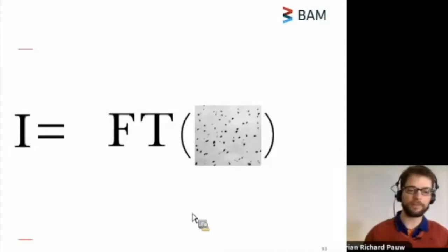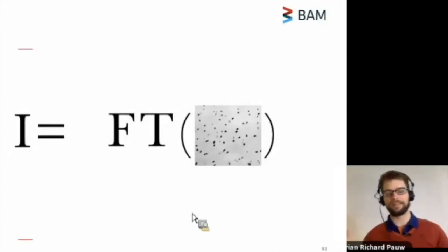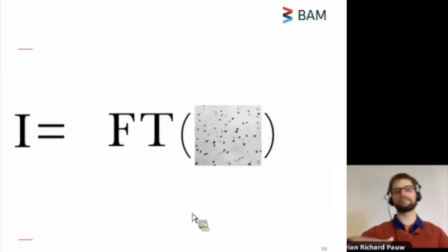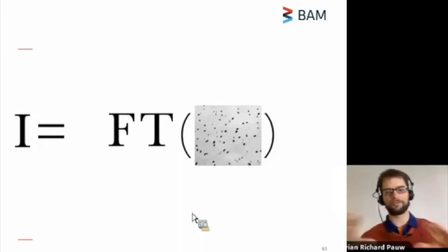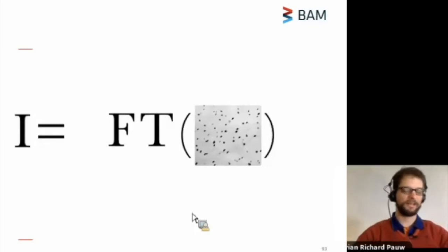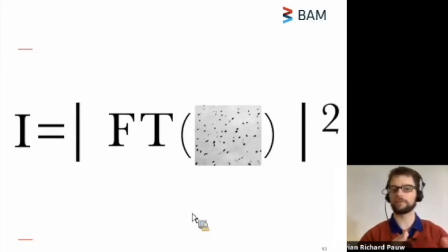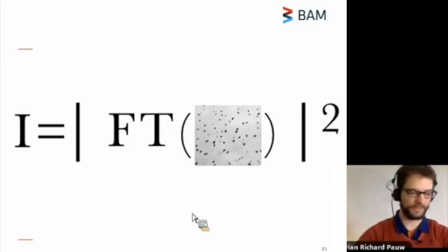And those of you familiar with Fourier transforms say, well, in that case, you can take your intensity and inverse Fourier transform it and get your three-dimensional electron density back. Unfortunately, that's not the case. Because we are not seeing the entire Fourier transform, we're only seeing the intensity component. So we've lost information, we've lost all the information on the phases. Now, this is the same phase problem that you have in X-ray diffraction, right? The same principles are going on behind this.